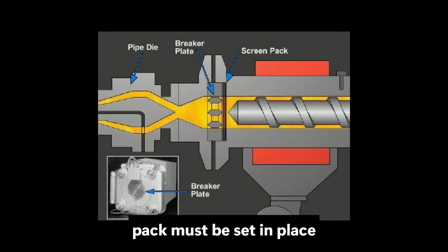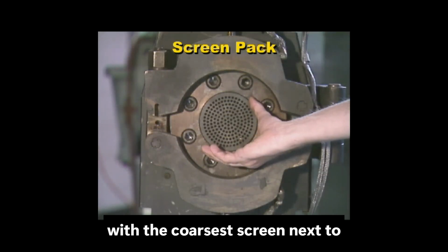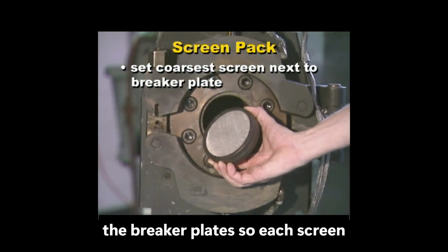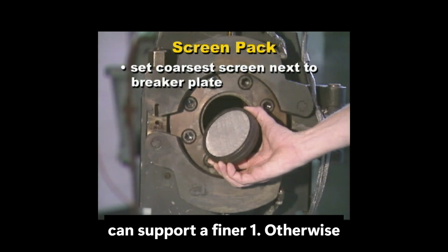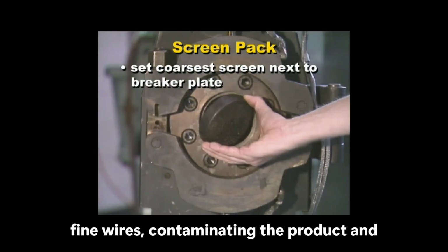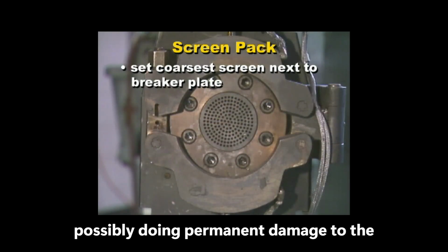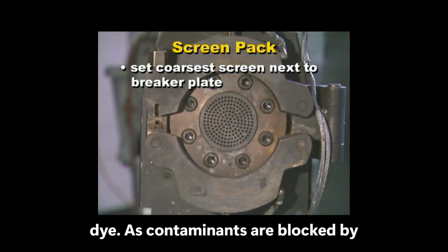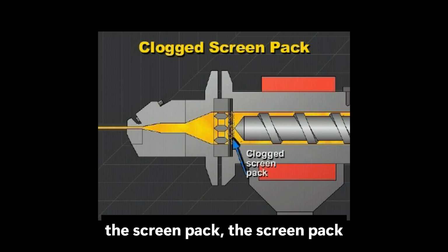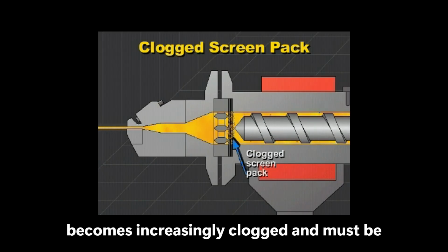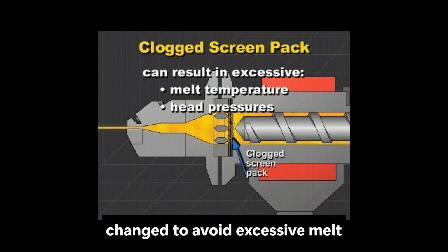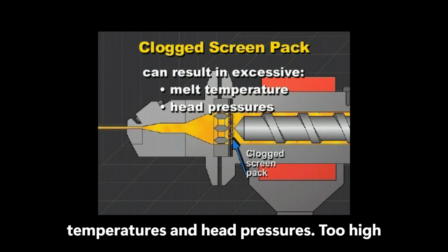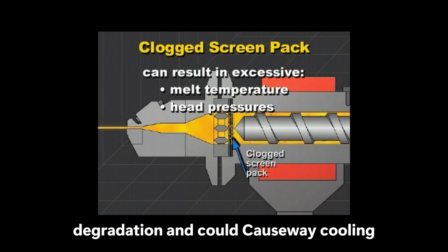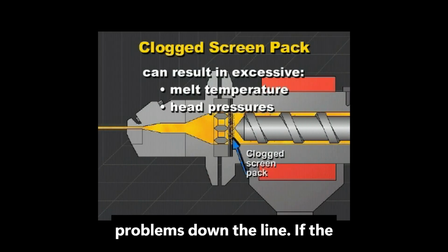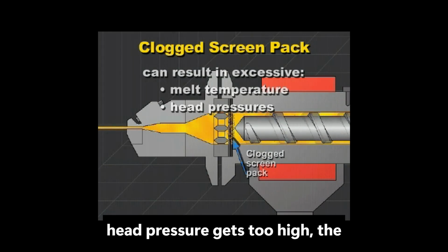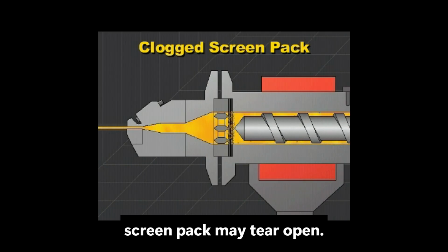The screen pack must be set in place with the coarsest screen next to the breaker plate so each screen can support a finer one. Otherwise, the pressure difference may break the fine wires, contaminating the product and possibly doing permanent damage to the die. As contaminants are blocked, the screen pack becomes increasingly clogged and must be changed to avoid excessive melt temperatures and head pressures. Too high a melt temperature can cause plastic degradation and could cause cooling problems down the line. If the head pressure gets too high, the screen pack may tear open.